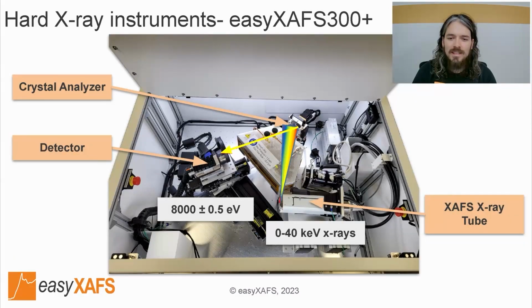So bringing that back into the context of the instrument, here we have a picture with the components illustrated. At a single position, the broadband 0 to 40 keV X-rays are generated by the X-ray tube, and then they're diffracted by the crystal analyzer and come back to the detector with a narrow bandwidth. Here schematically, 8,000 plus or minus around half an eV. As shown in the animation, we change the angle between the X-ray tube and the detector, so the diffracted energy changes, and then we go step by step, single acquisitions at each step, to build the X-ray absorption spectrum.